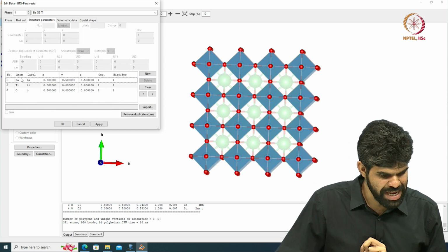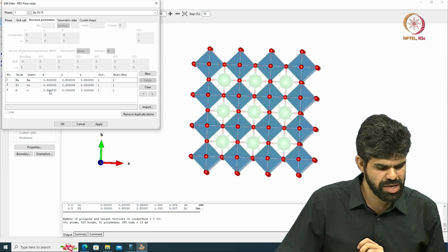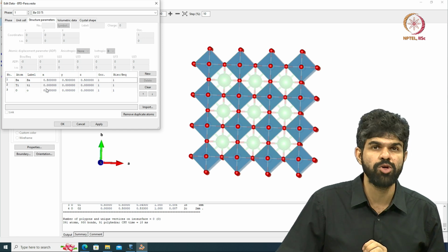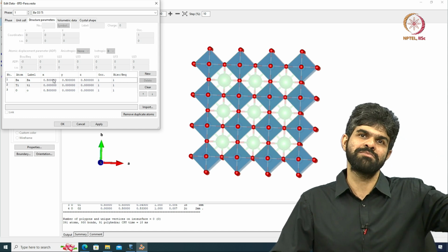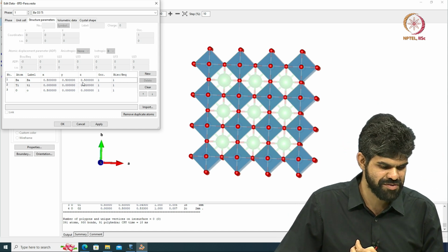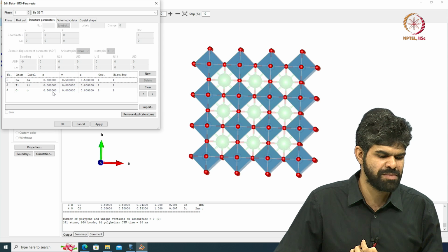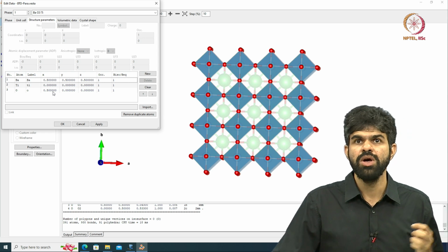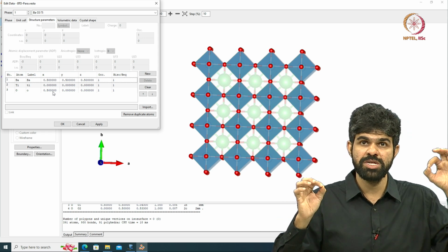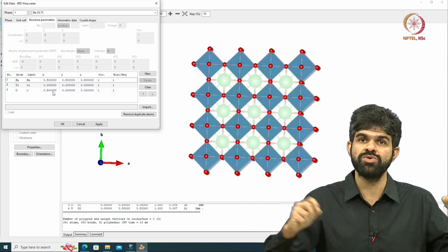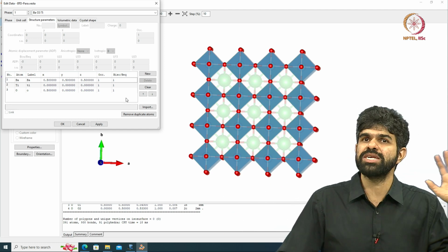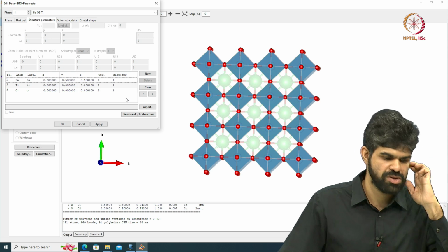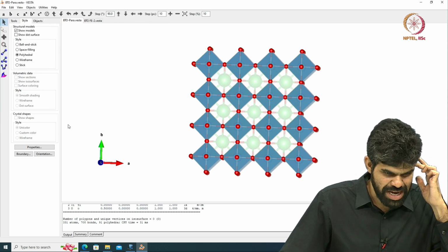And you see that bariums are at, okay, here the positions are slightly exchanged, they look at titanium as the origin. If titanium is the origin, barium then becomes the body center. Barium is at 0.5 0.5 0.5 and oxygen then becomes 0.5 0 0, so all 0.5 0 0, 0 0.5 0, 0 0 0.5, those are positions of oxygen. Very symmetric structure, very nice cubic structure. Alright, so that is the paraelectric phase.